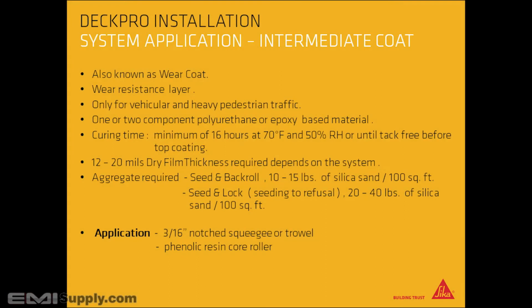Intermediate coat, also known as the wear coat. This is the wear resistance layer, only for vehicular and heavy pedestrian traffic. Use a 1 or 2 component polyurethane or epoxy-based material. Curing time is minimum 16 hours at 70 degrees Fahrenheit and 50% relative humidity, or until tack-free before top coating. A 12 to 20 mils DFT thickness is required, depending on the system being used.